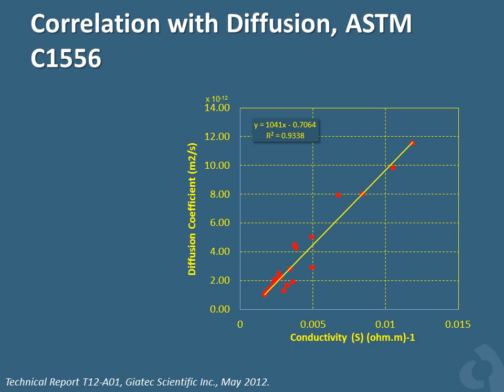It is proven that there is a strong relationship between the electrical resistivity of concrete and the diffusion coefficient of concrete. The diffusion coefficient is an important factor in the service life design of new structures, as well as for the maintenance and rehabilitation of existing structures. There is a linear relationship between the electrical resistivity of concrete in SSD condition and the diffusion coefficient, meaning resistivity can be used as a reliable technique to obtain the diffusion coefficient required in service life estimation of structures.